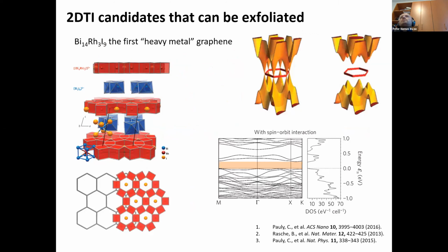Another part of this family that I have to mention is probably not so well known, but it's bismuth rhodium iodide. This was actually the first weak topological insulator to be shown to exist. So it's a topological insulator where you have protected Dirac cones only on certain faces. On the 001 face, you do not have any protected surface states. You can imagine it as a stack of quantum spin Hall systems.